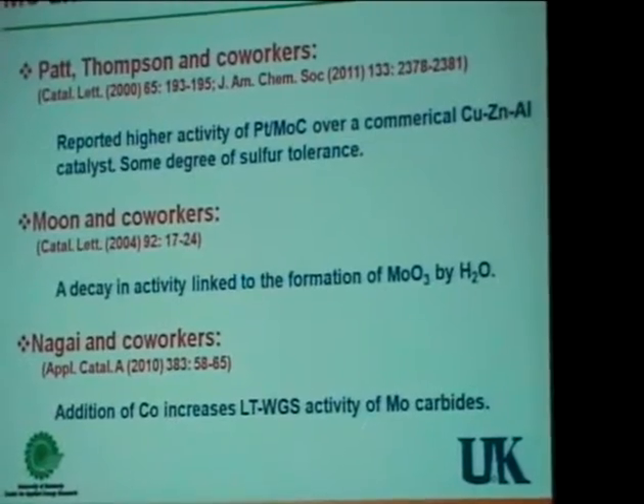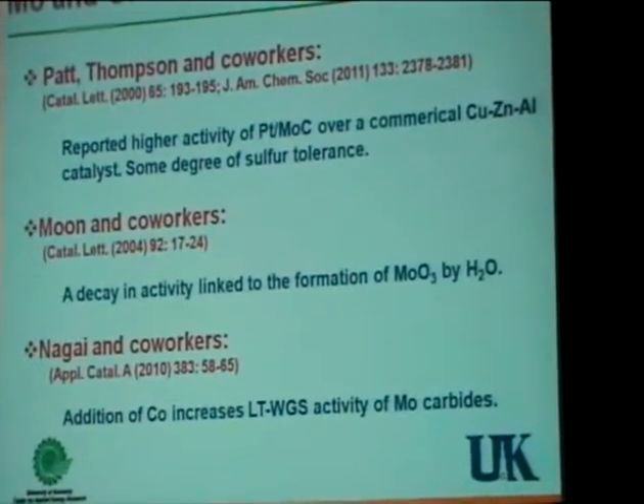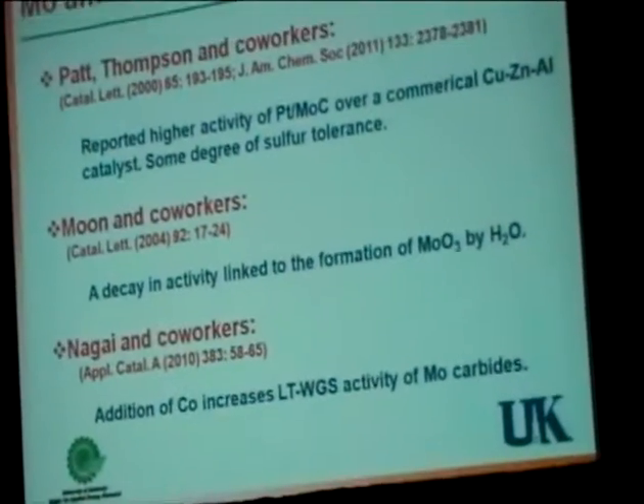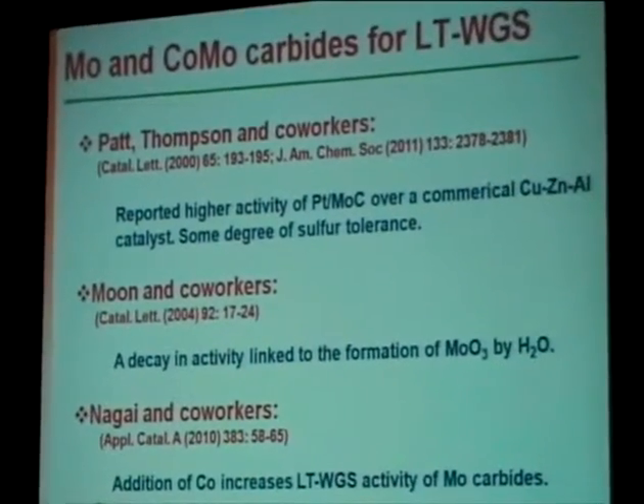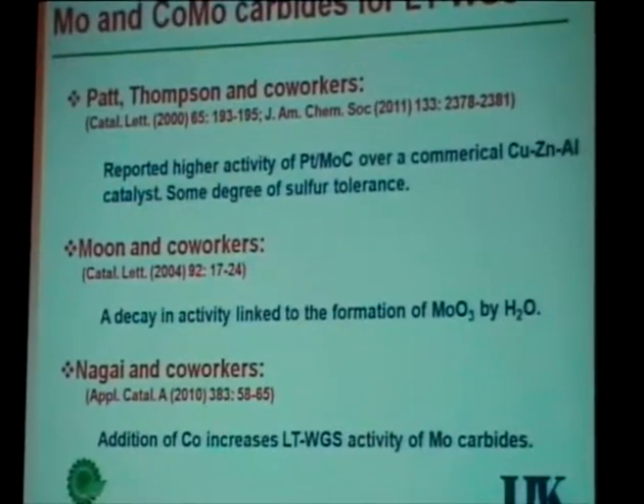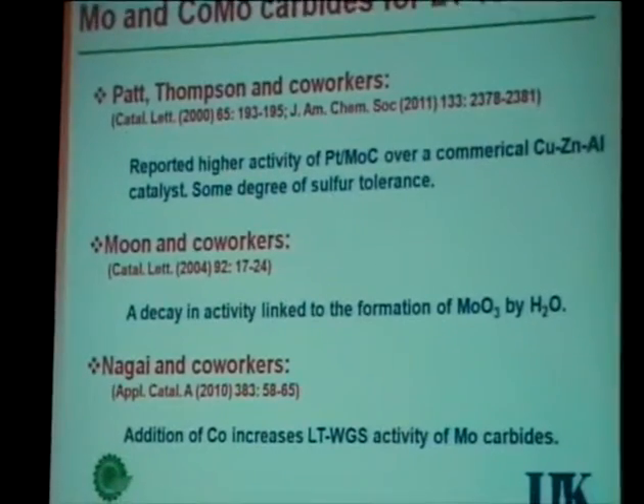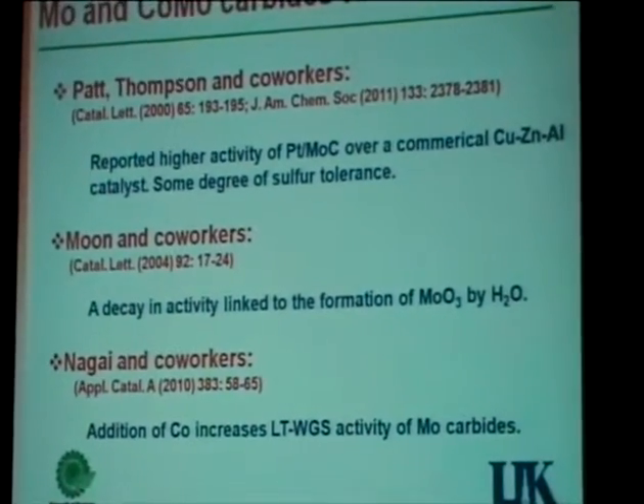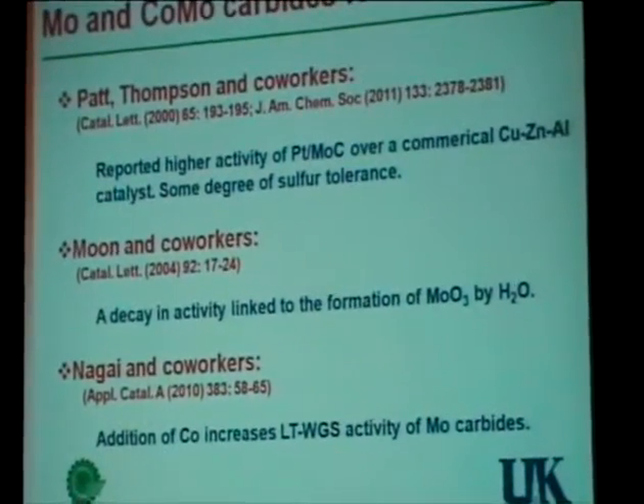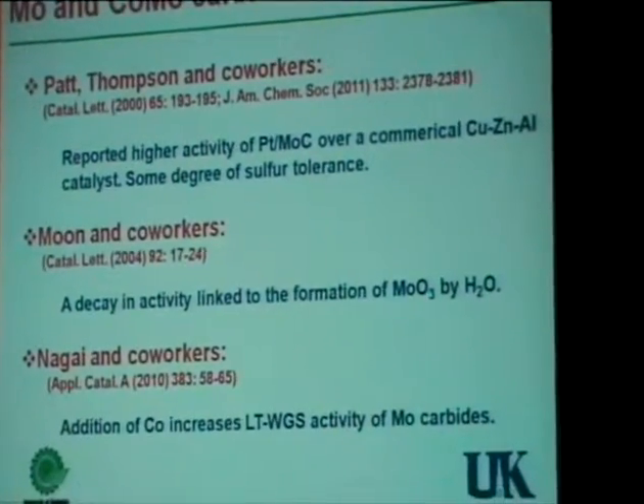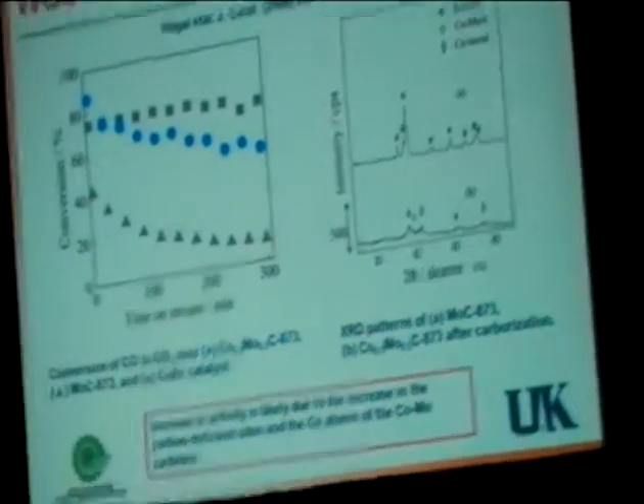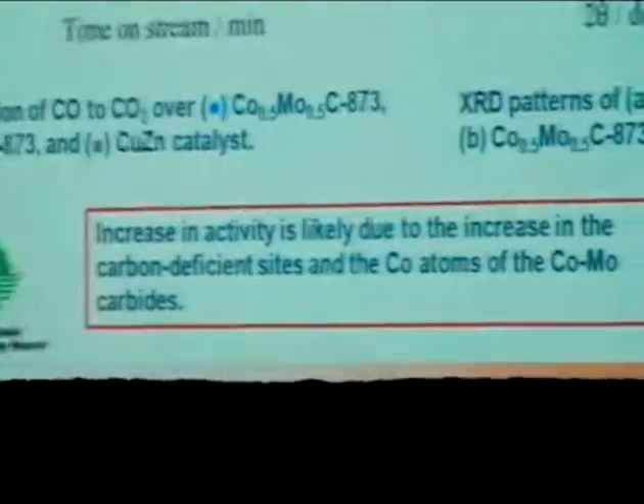So, and again, the Nagai workers have also shown that when you add the cobalt, you can stabilize the molybdenum carbide to some extent, and you can increase the water gas shift activity of the molybdenum carbide. So, in order to do so, I can just look at Nagai et al.